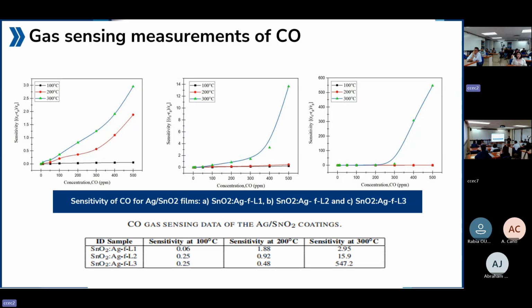At an operating temperature of 300 degrees Celsius and at a concentration of 500 ppm, we calculate that the sensitivity of the 3-layer immersed Ag tin oxide coating shows an approximate value of 547. This is very high compared to the other 2 films, which should be noted.